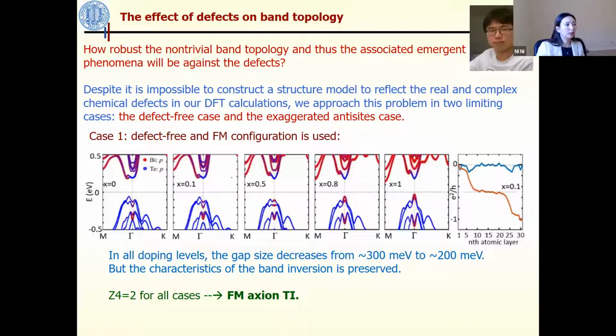The first case is the so-called defect-free ideal case, right? When we use this defect-free model, which assumes there was no defect, and then Tyrone did a band structure calculation, it turns out in all doping levels Z4 is equal to 2. So for all doping levels, the ground state is a ferromagnetic axion topological insulator.